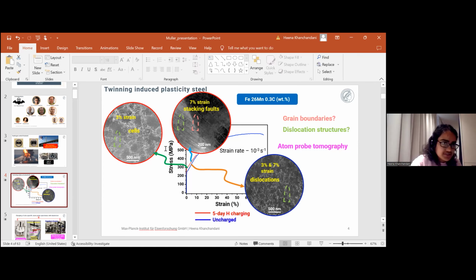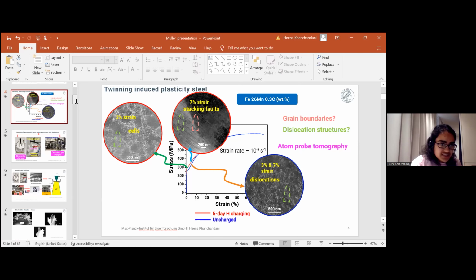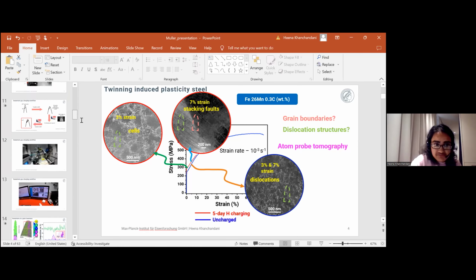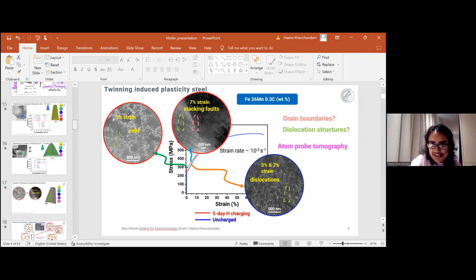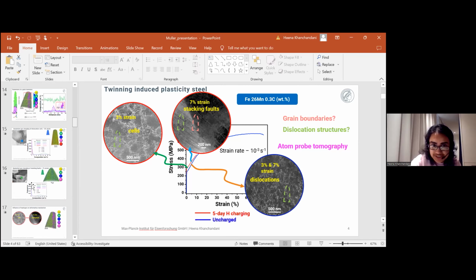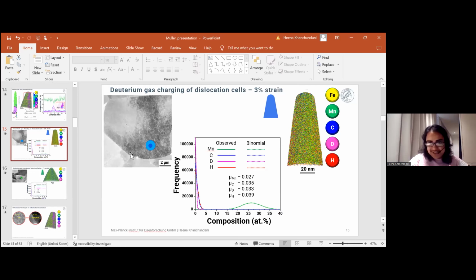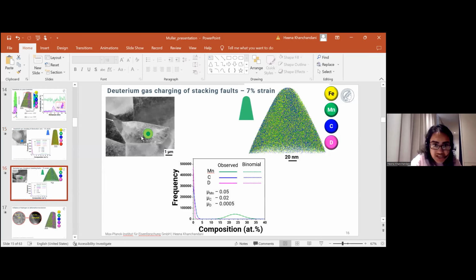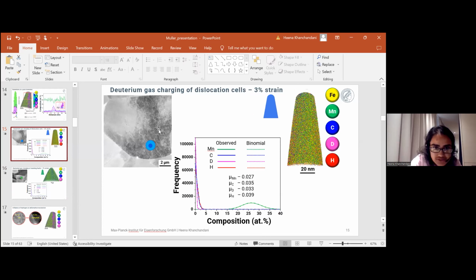So that is another reason. Third one, in this case, we simply missed the dislocation cell on the atom probe tip, or also the stacking fault, because I have done the cross-sectional lift out. I could not do the in-plane lift out for really capturing the stacking fault. So it is possible that I may have missed, because here also the size of these dislocation cells is somewhere around 500 nanometers, somewhere it is 1 micron. But also it might be possible that I may have missed an entire cell, but not a dislocation.